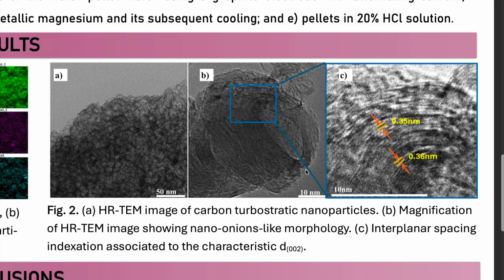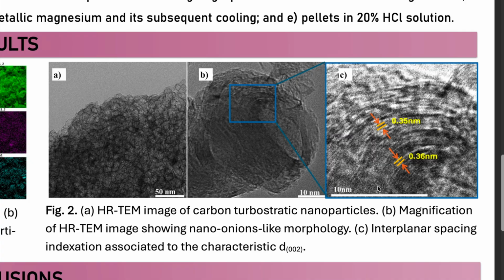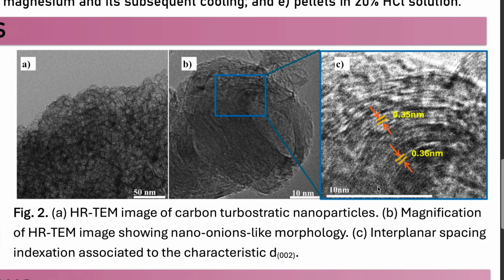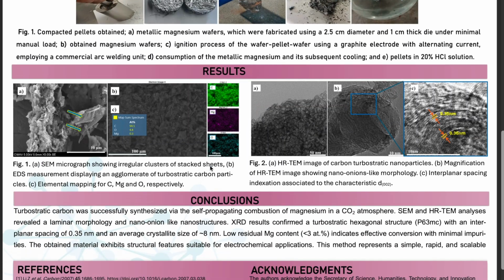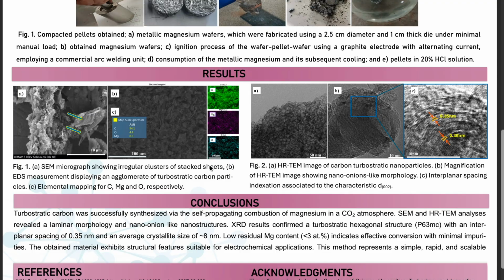Furthermore, Figure 2C illustrates the indexing of the characteristic D002 interplanar spacing at 0.35 to 0.36 nanometers, which is larger than that of ideal graphite, confirming the turbostratic nature of the material. These findings are corroborated by X-ray diffraction, which confirmed a turbostratic hexagonal structure belonging to the P63MC space group, with an average crystallite size of approximately 8 nanometers. Quantitative analysis showed a low residual magnesium content of less than 3 atomic percent, demonstrating the high conversion efficiency of the combustion process and effective acid leaching.